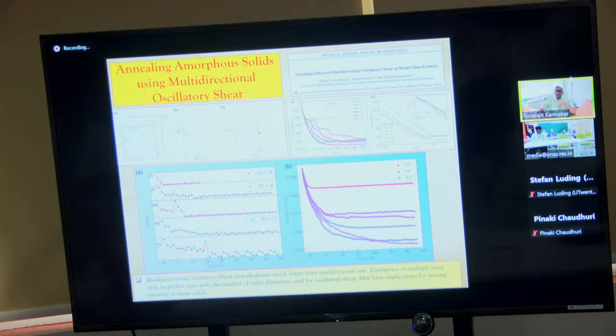So this energy scale turns out to have a very close correspondence with what an MCT energy scale is going to be. And why it is so, we do not have an answer, nor do the others who have worked on this. But what we looked at in addition is that instead of doing oscillatory shear along one direction, let's say in the XY plane, we introduced oscillatory shear along other possible directions. Particularly in 3D, you can have XY shear, and you can have YZ and ZX.